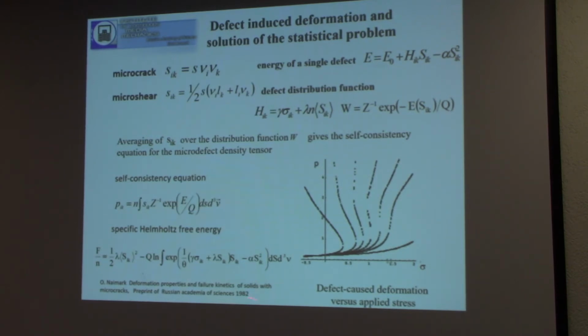At the end of the 20th century, a mesoscopic theory of defects was proposed. The idea was quite old. It's Kachanov's idea about an ensemble of cracks. We try to calculate the energy of each crack, try to do some averaging based on statistics, and we can obtain the additional deformation caused by this type of defect. If we are able to solve the statistical problems, we can determine, at least qualitatively, the form of the thermodynamic potential.